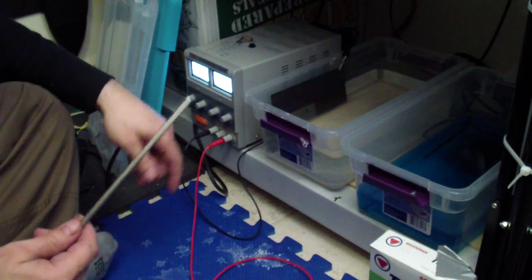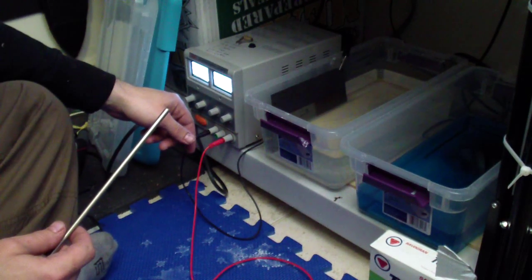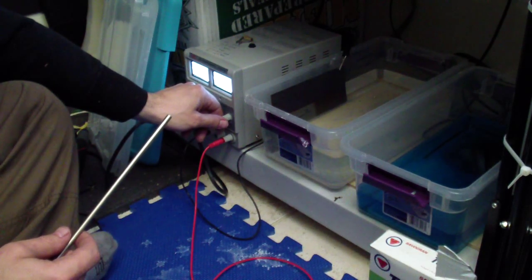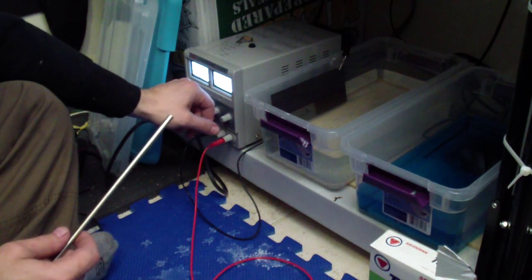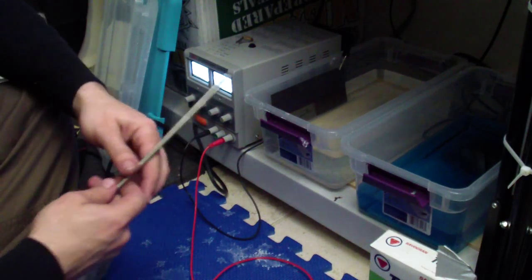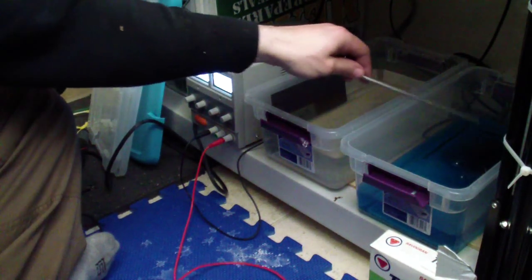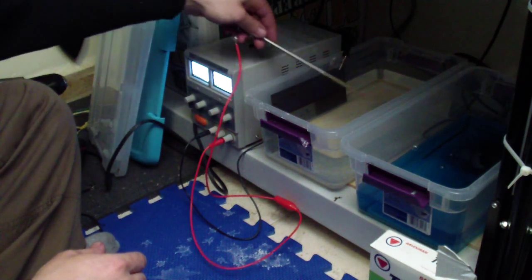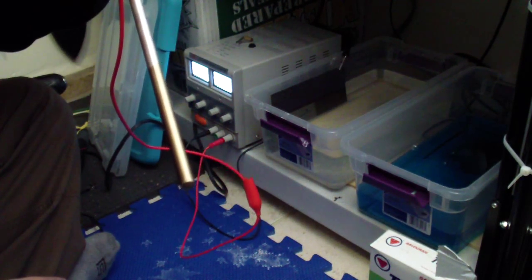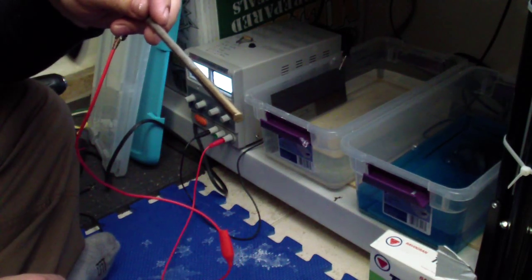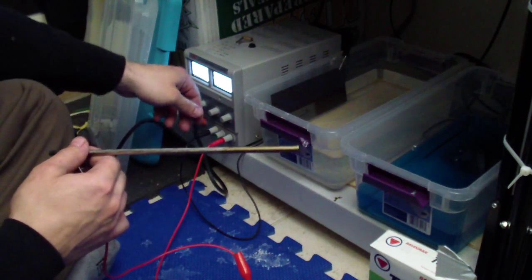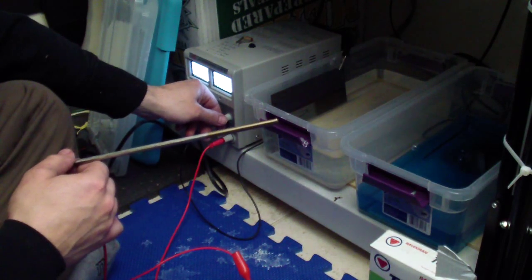I'm going to give you an example. 9.6 volts, I have it marked up here just for a little quick reference, is bronze. So I'm going to just dunk it in and you see how it changes color almost instantly. It's like a goldish, bronzish color.